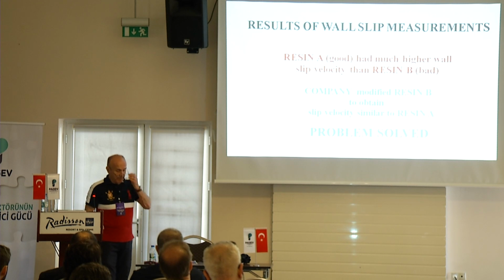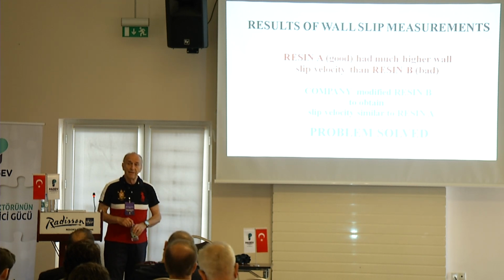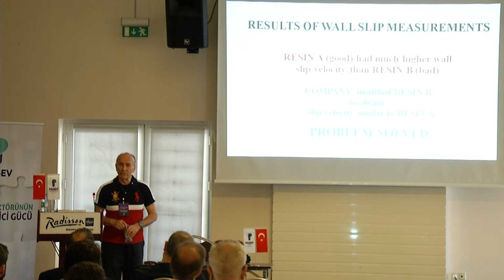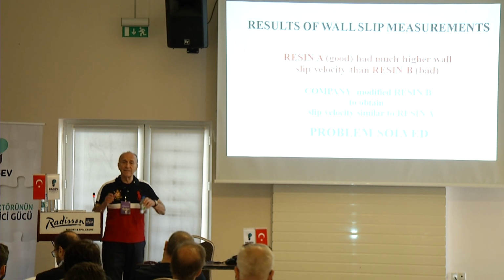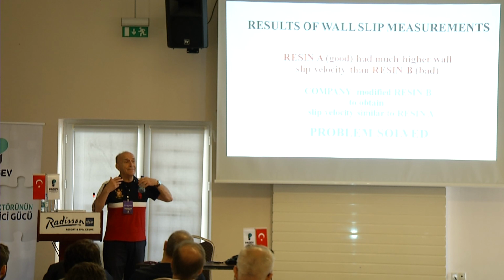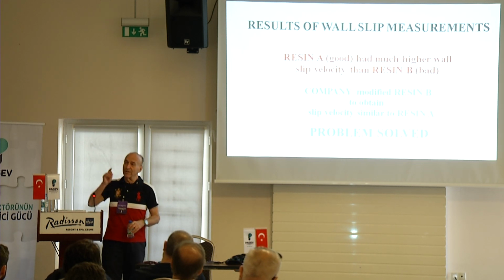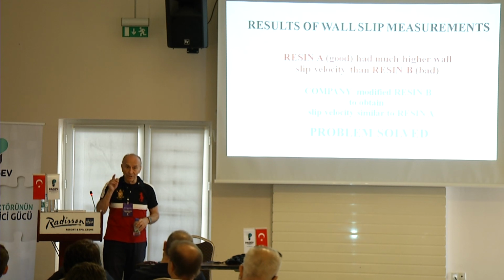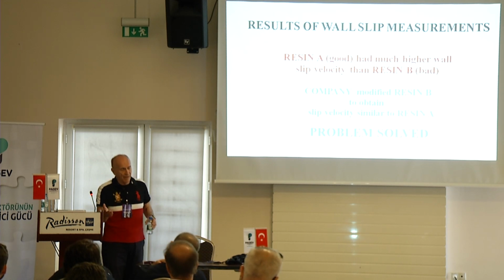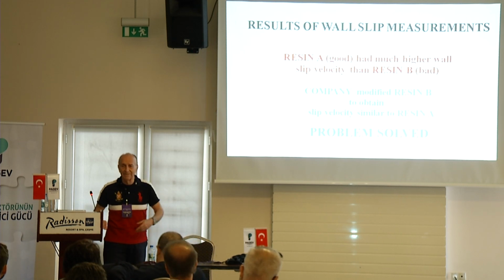And that was the problem. I told the customer, listen, the competitor resin has higher wall slip. It flows easily through the bridges, whereas your resin does not.